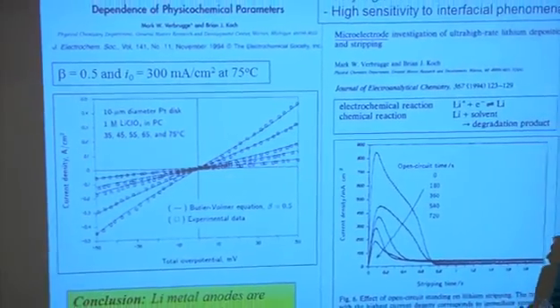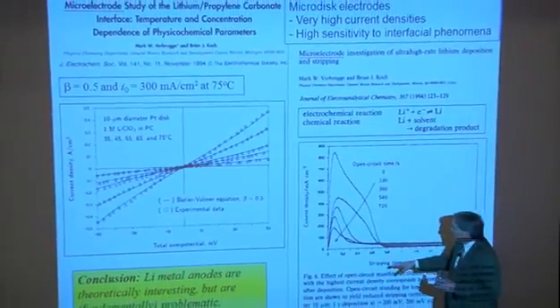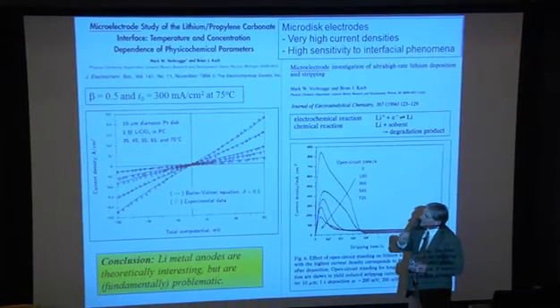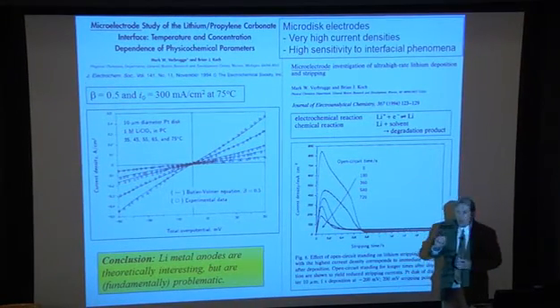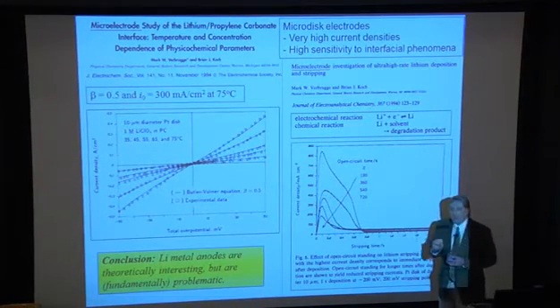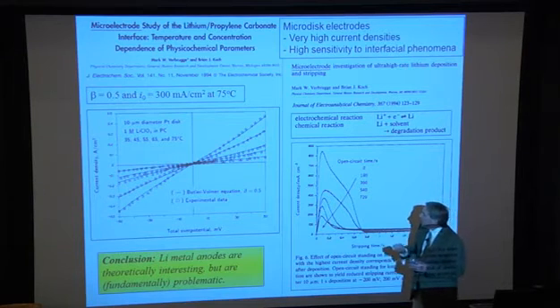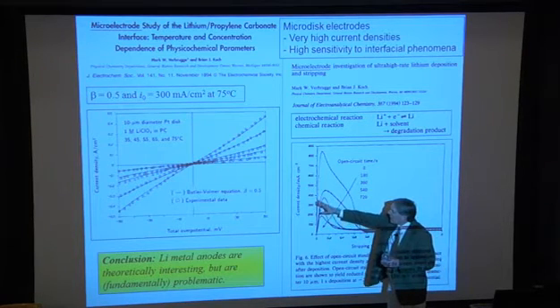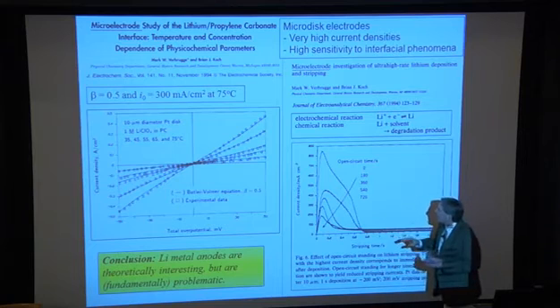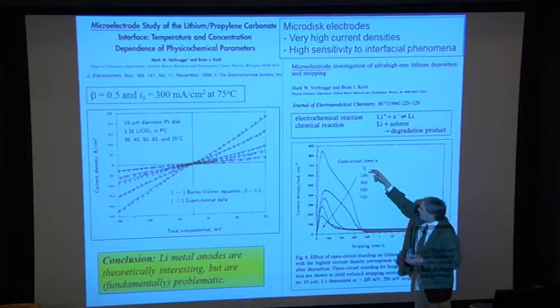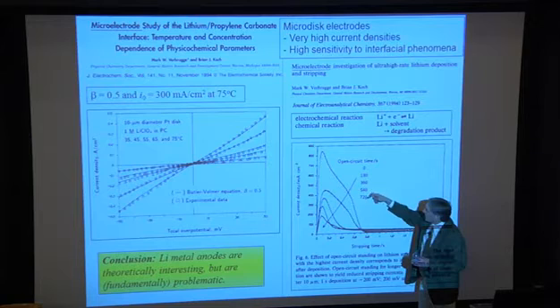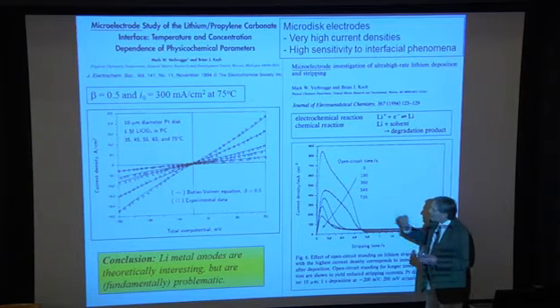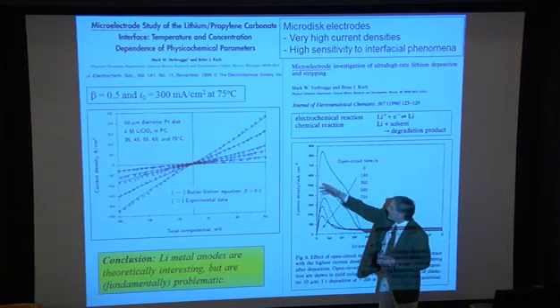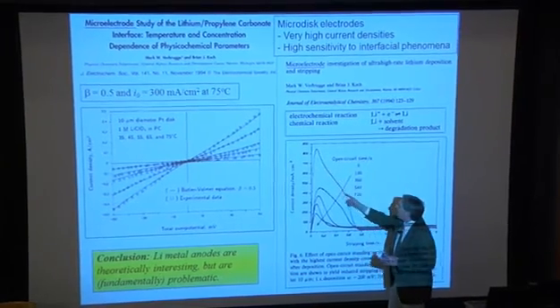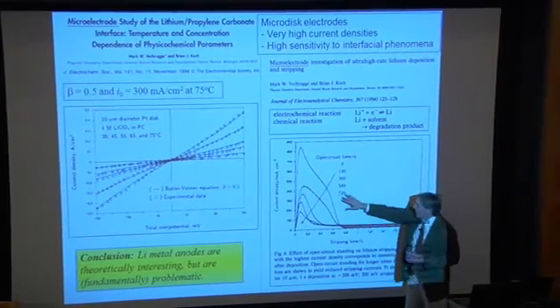and well understood. The problem is, this is a micro disc electrode, and that allows you to access more accurately electron transfer reaction rates. If you take the micro disc electrode, you deposit a little bit of lithium, and then you just wait. In this case, we wait for 0 time, 180, 360, 540, and 720 seconds. And after our wait period, we strip off the lithium. You strip it off over here, and you get a fair amount of material out.